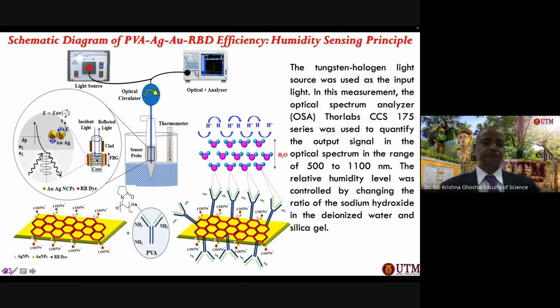So here is the measurement process of the sensors, because this is a very long discussion. If anyone is interested, we can discuss afterward how to make them and how to really exploit them for the measurement. And here is the mechanism of the rose Bengal dye-encapsulated silver gold nanoparticles together, because we know silver has a very sharp surface plasmon, gold has a lower surface plasmon than silver, but gold has stability. Gold is non-reactive and inert, and silver is a little reactive to oxygen.